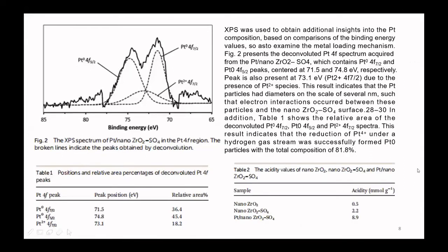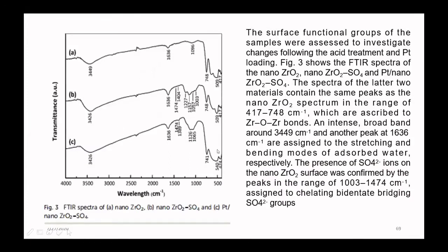The acidity of the nanomaterials increases after sulfation, and then also increases after insertion of the platinum, because the platinum provides Lewis acid. We can also see this from the IR spectrum. This one is nano zirconia. We use commercial nano zirconia, and in another case we use the precursor zirconium oxychloride.